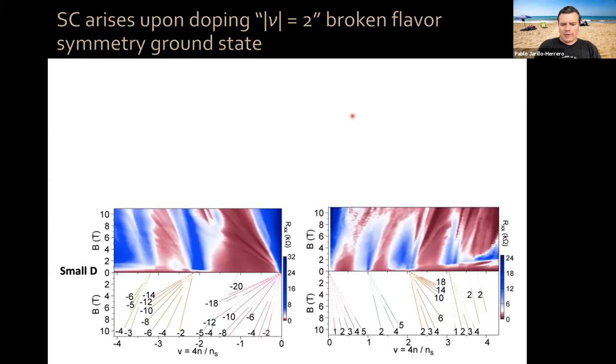We can look at small displacement field, and then as a function of magnetic field, measure the resistivity, and we look at the Shubnikov-de Haas oscillations and Landau fan diagrams. As you can see, both for electrons and for holes, in all of these fan diagrams you see Chern insulator states and all the topology. All of the Shubnikov oscillations point outwards, away from charge neutrality. Charge neutrality is here in the center. So on the right, all the lines go towards the right. On the left, all the lines go towards the left.